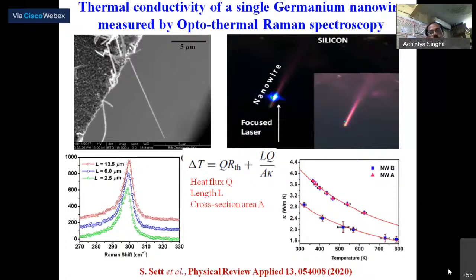Yeah, you can see that this delta T is Q RT plus LQ by AK. This is the thermal conductivity, and we know all the parameters. That is, Qt is the flux equivalent temperature depending on the laser power, L is the length, and A is the cross-sectional area of the nanowire. And from this Raman measurement, we got the thermal conductivity, and we also did the temperature-dependent thermal conductivity using this measurement. Okay, go next.